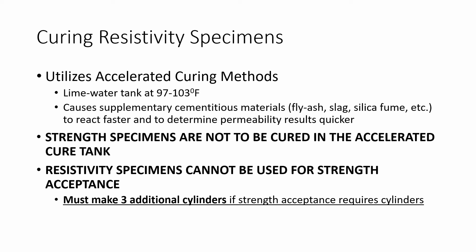The heat from the accelerated cure procedure will cause the reactions of the SCMs to accelerate, which then will help us determine the potential permeability of the concrete. More on this procedure will be covered later in the video. The one thing that needs to be made clear is that strength specimens are not to be cured in the accelerated cure tank. This is not an acceptable method for curing strength specimens.